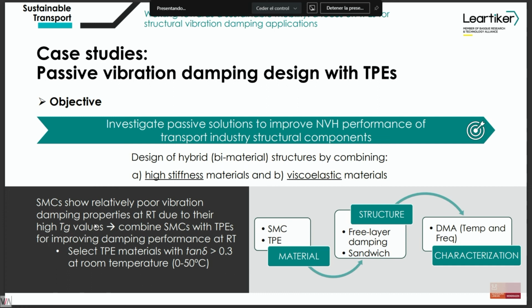So as I mentioned, as SMC has this relatively poor vibration damping at room temperature mainly, due to, as we will see later, the high glass transition values of these materials, we combined SMC with TPE for targeting improvements of the vibration damping at room temperature. So for that, the first thing was to select TPE materials with loss factor values higher than 0.3.